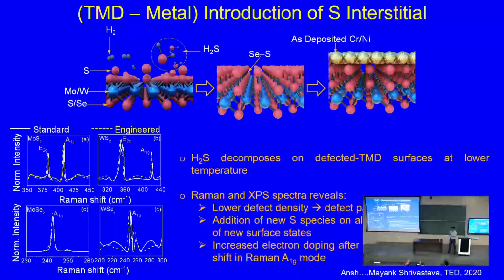So we introduced additional sulfur atoms at interstitial sites, and then put metal on top of that. Depending on the metal, chromium or nickel, we get either acceptor states or donor states. We confirmed this with various techniques, Raman and XPS, to ensure that the material is intact. This is still 2D TMD, the band gap is intact, it's still semiconducting and so on.